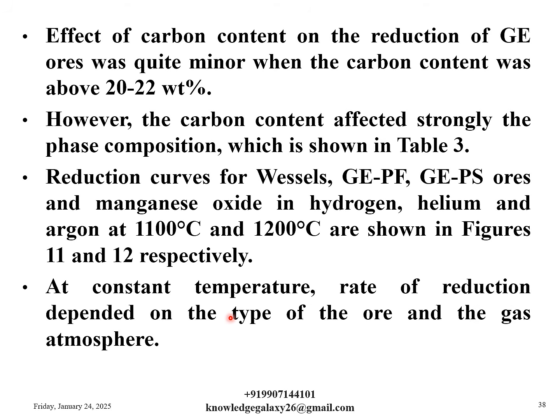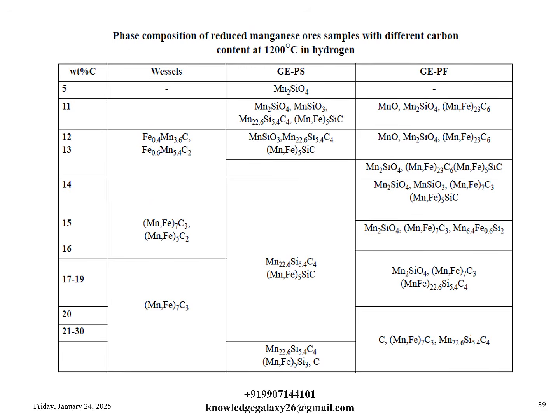At constant temperature, rate of reduction depended on the type of ore and the gas atmosphere. So this is the phase composition of reduced manganese ore samples with different carbon content at 1200 degrees Celsius in hydrogen. So this is table 3 as mentioned above. You can pause the video and observe the contents.